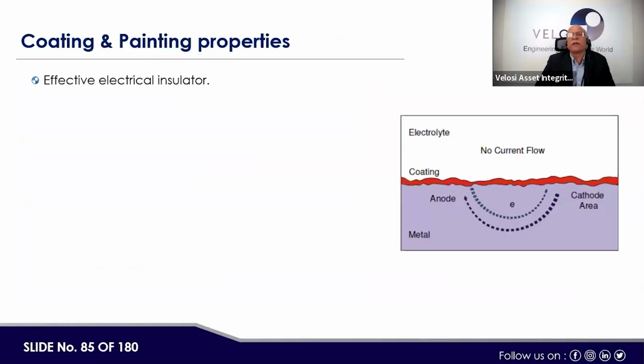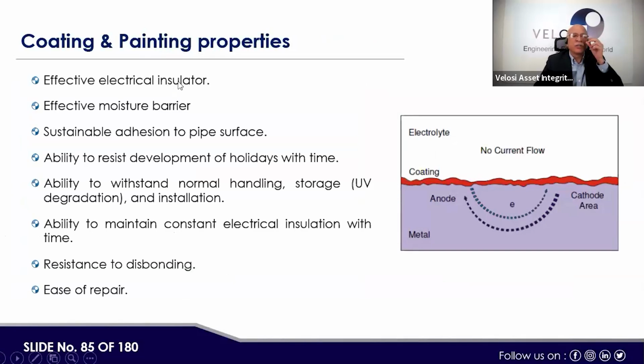From the properties point of view, we see effective electrical insulator, effective moisture barrier, sustainable adhesion to the pipe surface, ability to resist development of holidays with time, ability to withstand normal handling, storage, and installation, ability to maintain constant electrical insulation with time, resistance to disbonding, ease of repair. If you see here, this is the coating, and the electrolyte is above, and this is the metal of the pipeline. Non-toxic interaction with the environment is also one of the criteria.